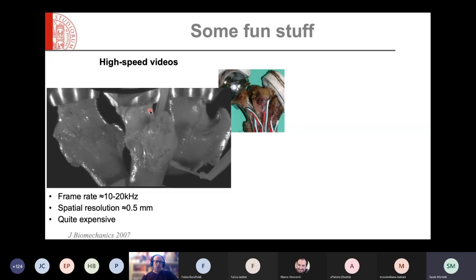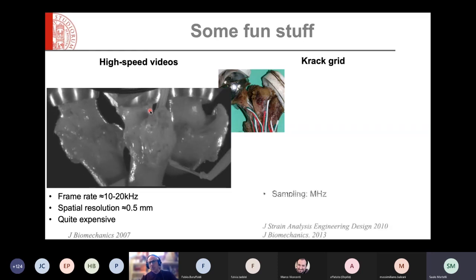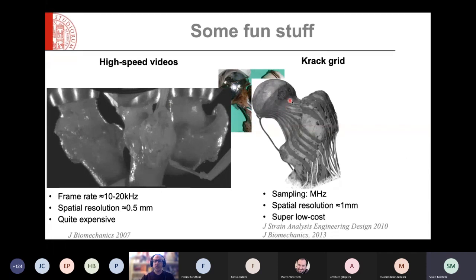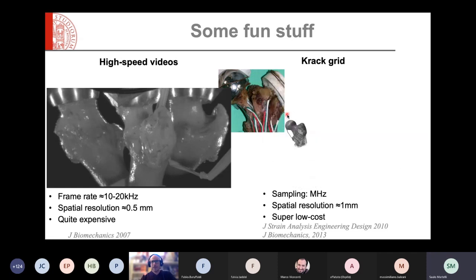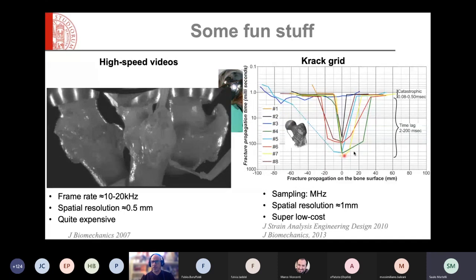It's also very expensive. One day, again, Mateusz came to my office and said, why don't we just paint very tiny lines on the femur with a conductive paint, which you can buy in a shop and connect them to a CPU so that you can sample them at a few megahertz, and when the line breaks, you monitor a fracture. And I said, good idea, why don't we try? And this is the result. So here you see that fracture starts at certain points, but this is just one line cracking, then nothing happens for a few hundreds of milliseconds. So the femur is taking up energy before catastrophic fracture occurs quite some time later. So in a way, Mateusz was able to observe how fracture starts and propagates in the femur in a way that could not be seen just from this sort of video.